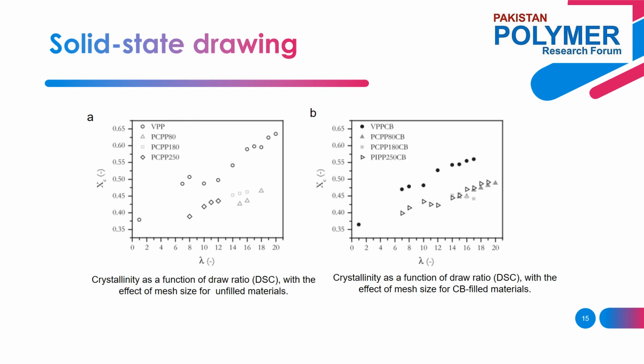Figure A and B shows the evolution of crystallinity for unfilled material and carbon black filled material, both as a function of draw ratio. The crystallinity increases with the increasing draw ratio, and the crystallinity of recycled material is lower than the virgin isotactic polypropylene. Focusing on the differences between recycled materials, it is seen that melt filtration size doesn't affect the crystallinity. Filters separate solid particles such as PET of size much greater than the lamellar thickness. Therefore, the crystal formation is not hindered.